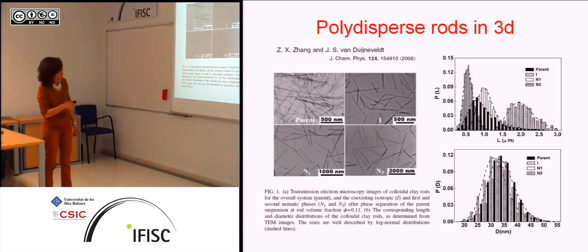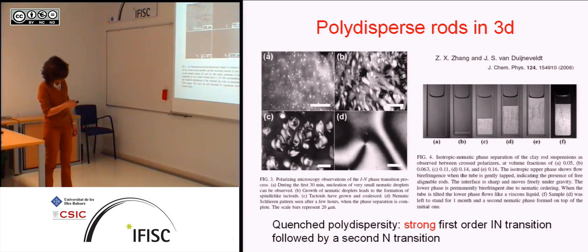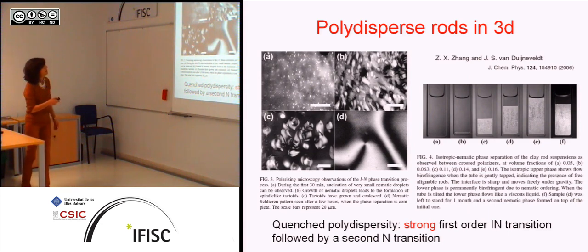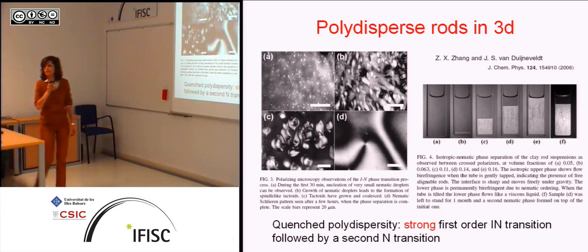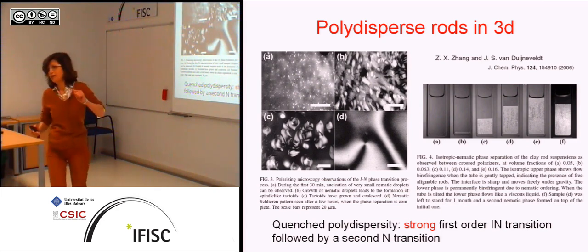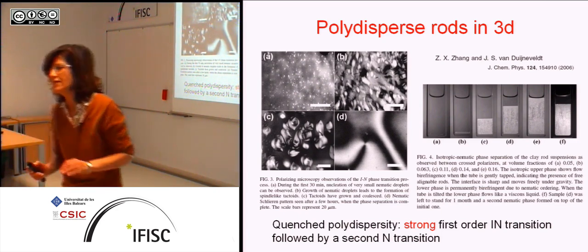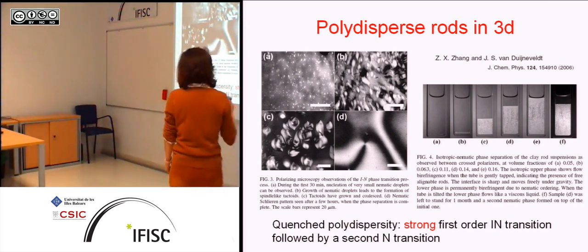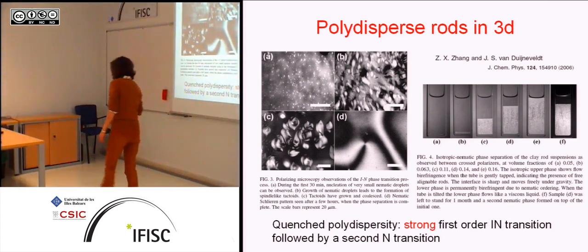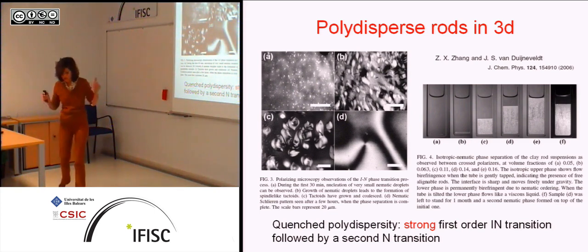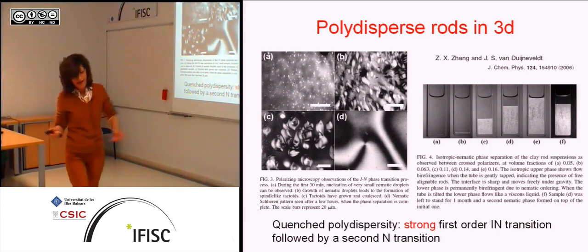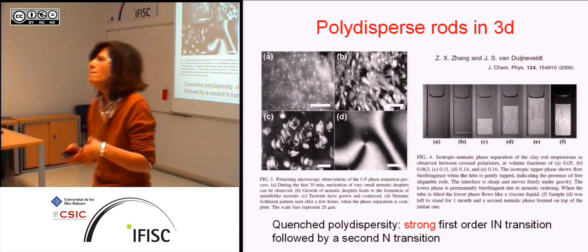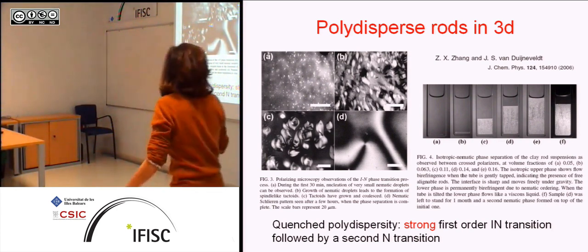And of course these are the distributions in the various phases. But the surprises, or not, come later. Actually, this is just the nematic one forming after the phase separation. If you wait long enough, there is a second nematic phase that appears. And nobody really understands if that's just because the relaxation is much, much slower in this second nematic, or what's going on here. So there are two things. The transition becomes more strongly first order, and there are new phases that appear. They seem to have very different dynamics, at least very different time scales.